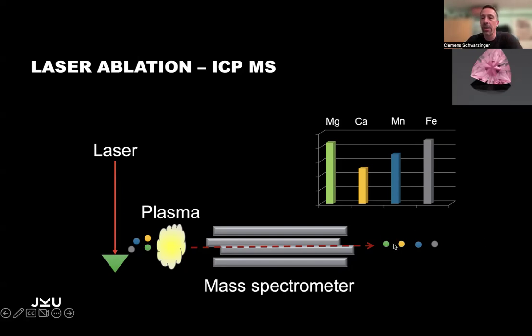And what we get is the greens, the yellows, the blues, and the grays. Here we have called them magnesium, calcium, manganese, and iron. And we get the concentrations. And if we have the concentrations of these elements, again, we can go into calculations and get the theoretical composition of our garnet. Now, what is the problem with this instrument? Mostly its price. You're talking about 300,000 US dollars and no upper limit. You can go as high as you want, depending on the laser and the mass spec that you're using. So this is something that you don't have in every lab.